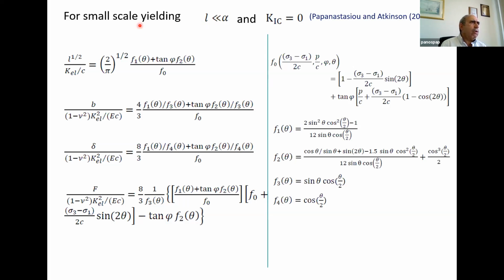So with this analytical model, in some particular cases, like small scale yielding, when the plastic zones are much smaller than the fracture length and the fracture toughness is 0, it's possible to derive the equations in dimensionless form, as you can see here, for the length of the dislocation and the crack opening displacement. B is the strength of the dislocation, delta is the crack opening displacement, and there is the force, which is a good measure of energy to propagate a fracture.